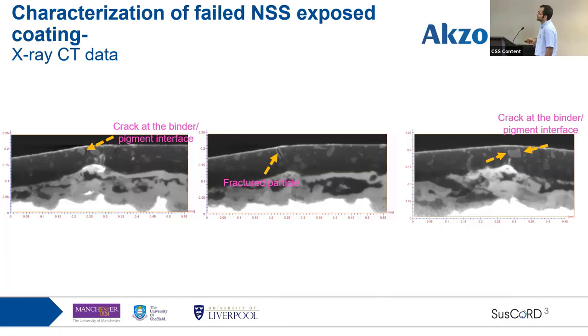But these are within the coating, and in the case of the samples that were exposed to the cyclic corrosion test, we could consider them forming during the exposure, but here the sample was exposed only to the neutral salt spray test. But since they are also in the center, when the blister formation is happening, it is possible that the stress generated within the coating due to the blister formation results in the formation of these cracks.